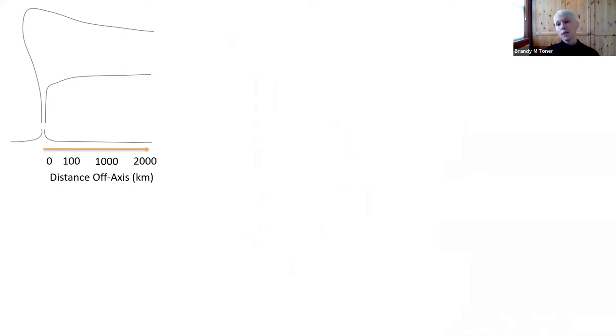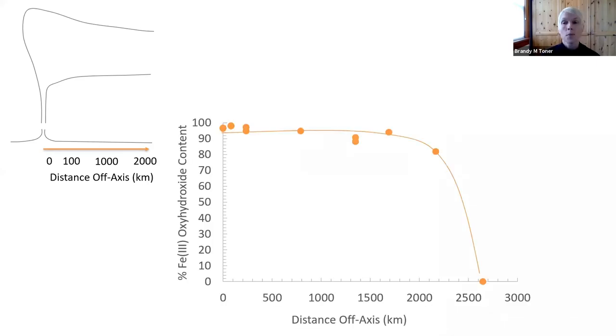So we fit these XAFS data with linear combinations of reference materials. What I'm going to show you is a plot that describes some of that speciation. So on the y-axis here, I'm showing the atom percent iron 3 in the form of an oxyhydroxide. So you'll notice that it's right up at 100%. So these are iron 3 oxyhydroxides. And on the x-axis, you can track out the distance from the hydrothermal source. You'll see that the iron 3 oxyhydroxide content starts to turn over somewhere between 2000 and 2500 kilometers off axis and crashes out here.